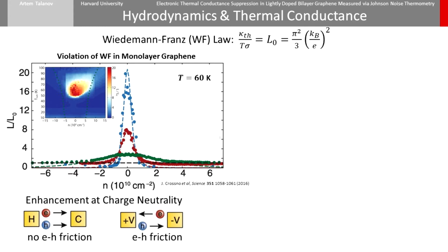We can understand this by considering the effect of a thermal or potential gradient on electrons and holes. In a thermal gradient, the electrons and holes move together unimpeded, but in a potential gradient, they move in opposite directions and generate electron-hole friction. The lack of friction in the thermal transport sector gives us such a large enhancement.